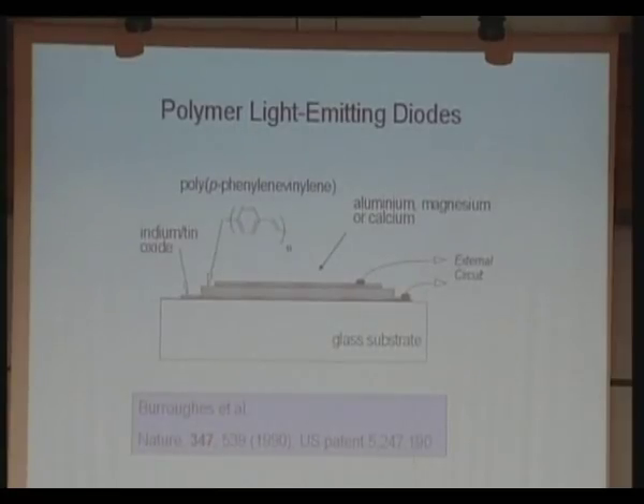This is a cartoon going back a few years. We published a paper in 1990 showing how it's possible to make the simplest possible semiconductor device, which is a sandwich of semiconductor, that's the green slab, between two metals. The one on the bottom here is a transparent metal, indium tin oxide, pre-coated on a glass substrate. We've then literally painted down a film of polymer from solution, and then we've evaporated a top electrode on, which is usually a low work function metal such as calcium.